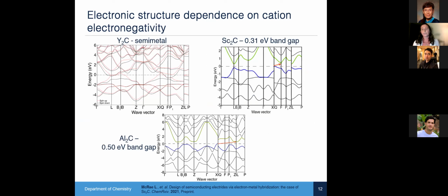We wanted to again explore how electronegativity could affect the band gap. And so we calculated for the aluminum carbide structure what the band gap would be, and found that again, it splits even a little bit more. So now we get a half an eV band gap. And so our conclusion here is that based on the electronegativity of the cation that you're incorporating into these structures, you can actually tune the band structure to get anywhere from metallic structures to wider band gap semiconductors. And that's what we're showing here.